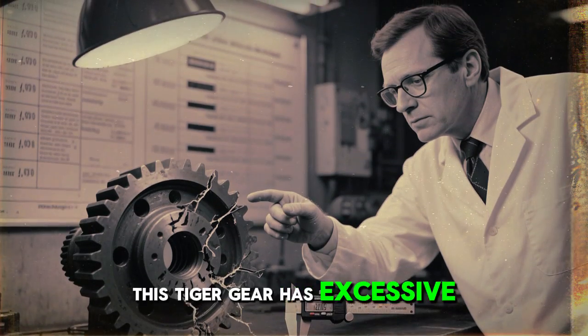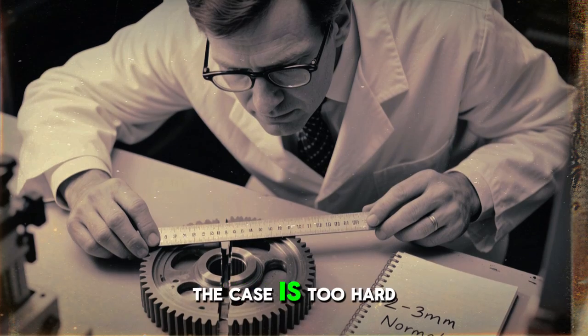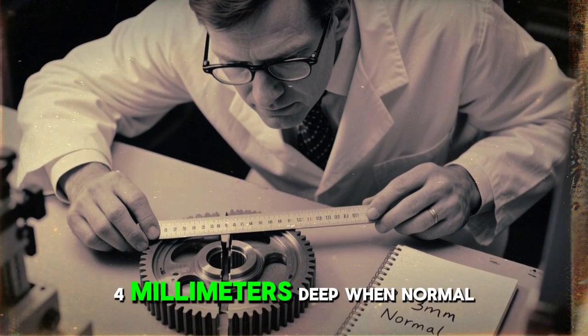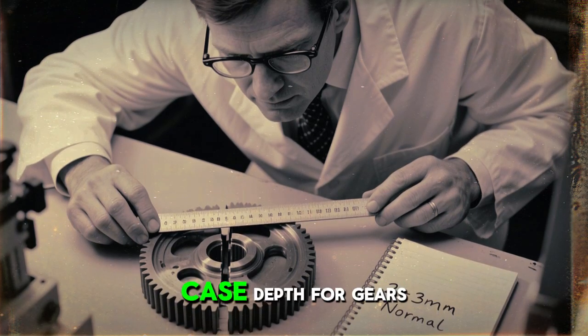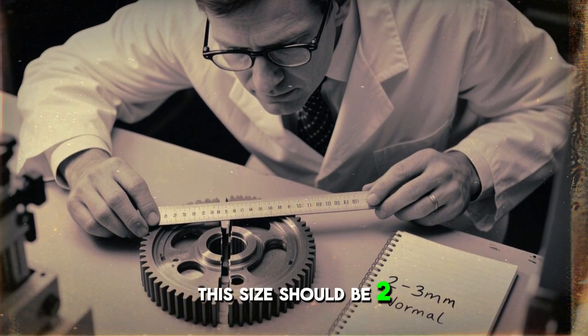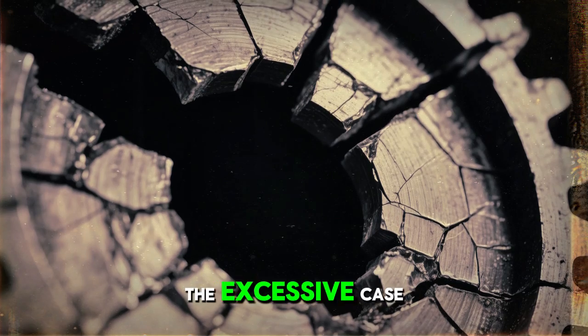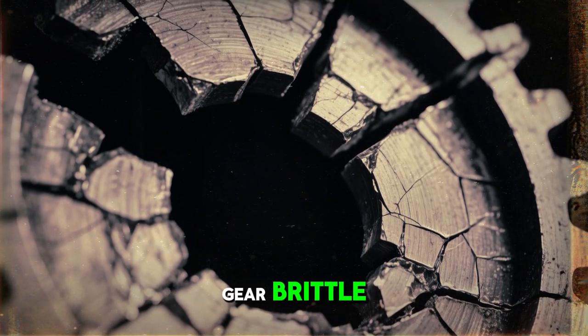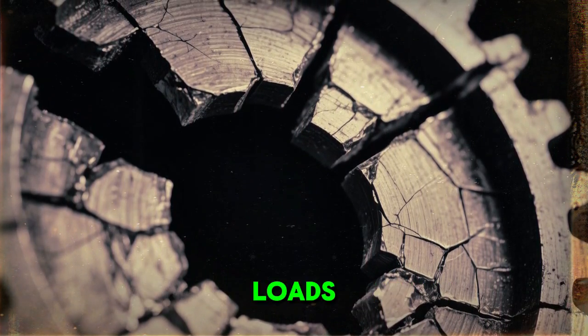This Tiger gear has excessive surface hardness. The case is too hard and too deep, 4 millimeters deep, when normal case depth for gears this size should be 2 to 3 millimeters. The excessive case depth and hardness make the gear brittle, prone to fracture under heavy loads.